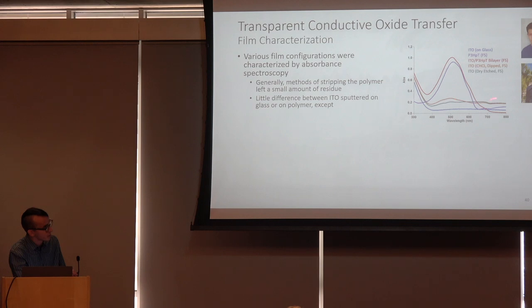And as you can see, there's these little features here, these small peaks, which still correspond to the polymer peaks. So there's some residual polymer remaining, even after etching slash stripping. And then additionally, there's an apparent increase in absorption across the entire spectrum. Now, we're not sure that is real absorption. The UV-Vis, the instrument that we were using for these measurements, the way that the measurements are performed is that you're just measuring the amount of light that is transmitted through, right? So the instrument has no way of actually differentiating between light that was truly absorbed and light that was just reflected.